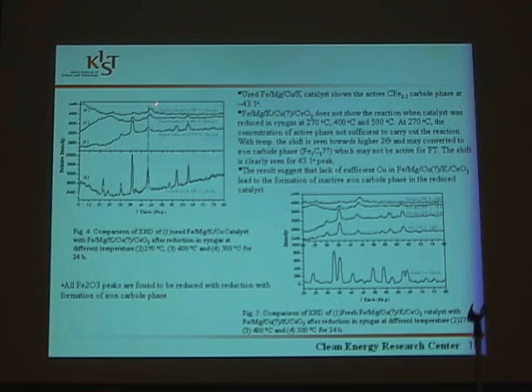This has shifted to the right side, to the higher 2-theta value, and that is the reason why this catalyst has not shown the reaction, because whatever iron carbide phase has formed was not active for the FT reaction. That is why, when this catalyst did not show any activity, we impregnated it again with copper, and later on this catalyst has shown activity.